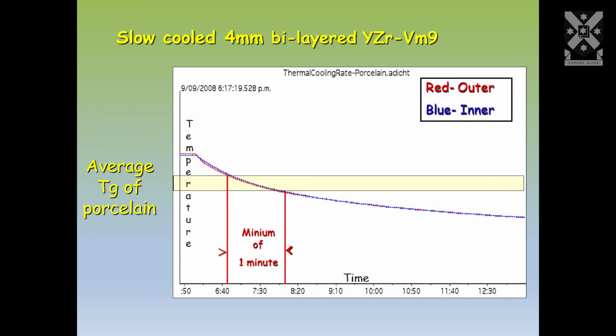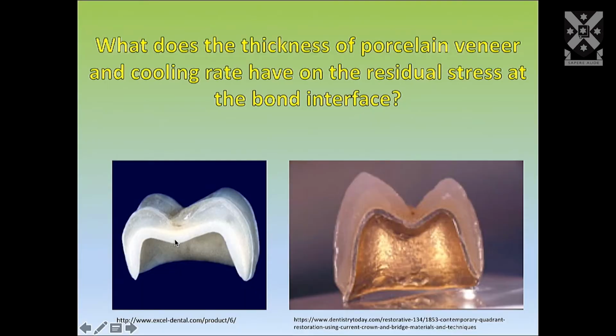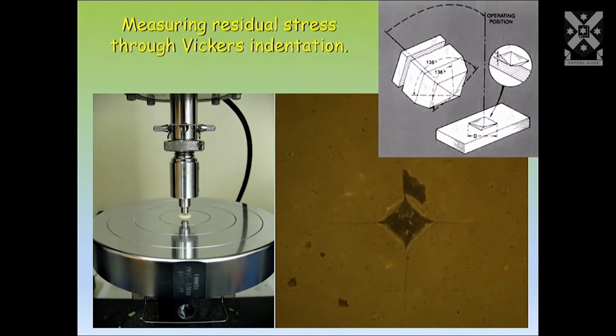And as I said, we were using cobalt chrome and we were using all ceramics, and that's why I've shown here's a metal substructure and there's an all ceramic substructure. So looking at the all ceramic, we use indentation. So we take this little Vickers diamond, it's got a set shape, and we indent it into the surface of the porcelain, and you see these little cracks.